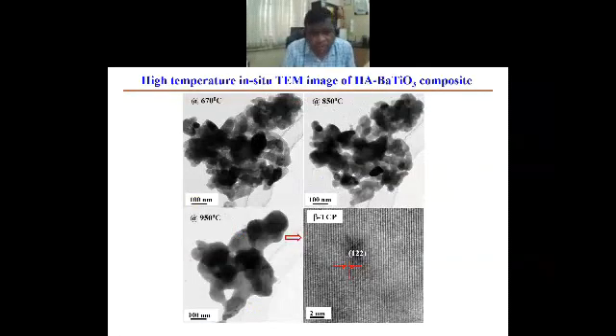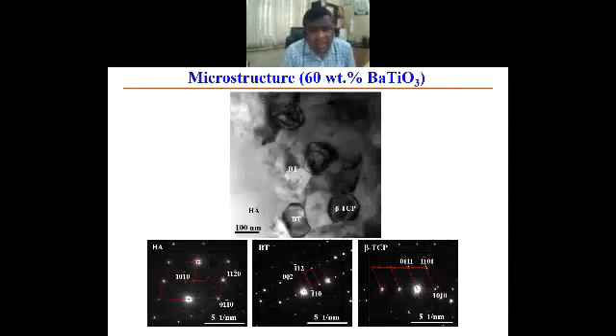So we have also been trying to understand, at different temperatures by in situ high temperature transmission microscopy, whether this hydroxyapatite barium titanate dissociates, and what the evolution of the beta TCP is, for example, when you heat it to 950 degrees Celsius. And what we have found in the sintered hydroxyapatite barium titanate composites is that barium titanate and beta TCP are both retained in the microstructure.